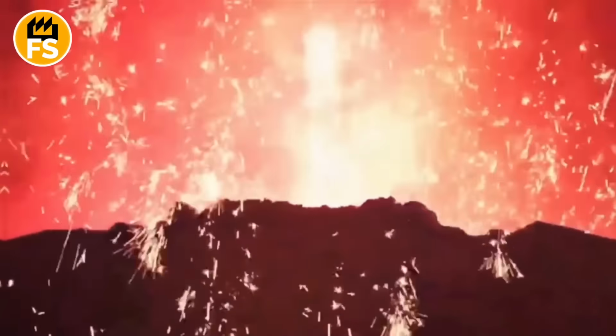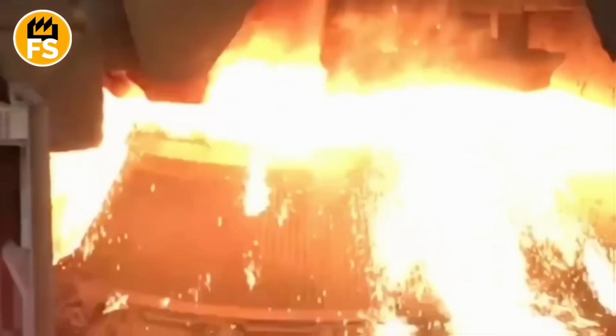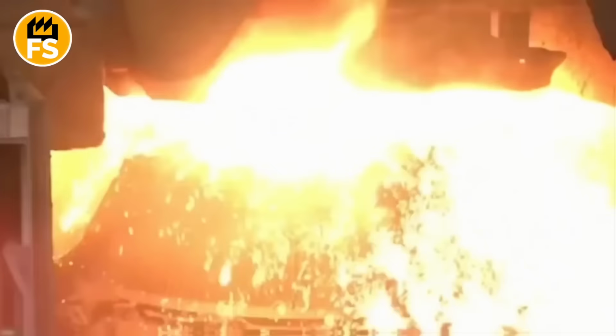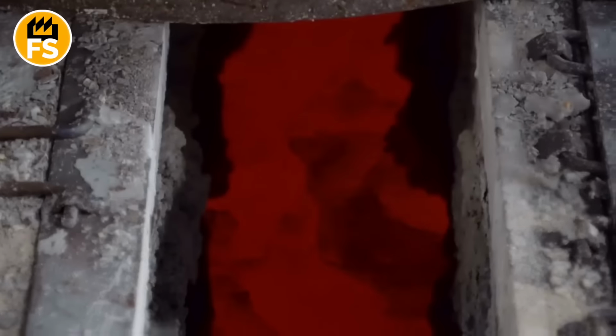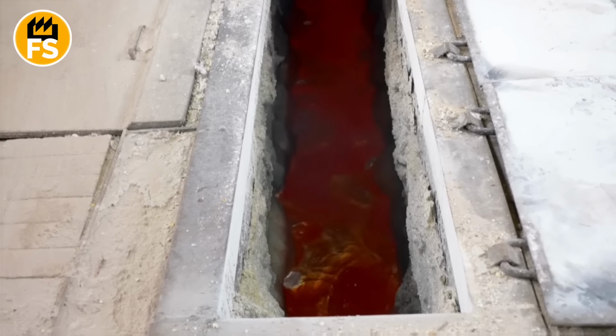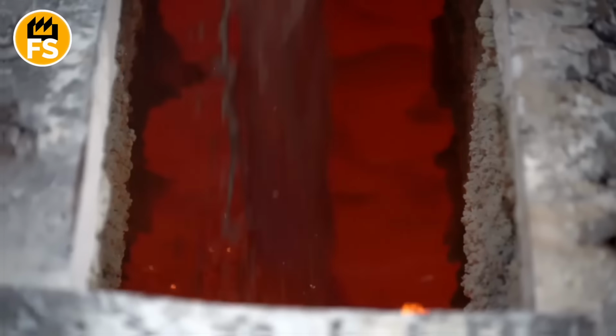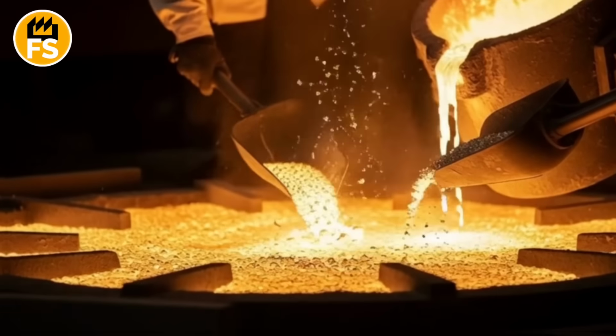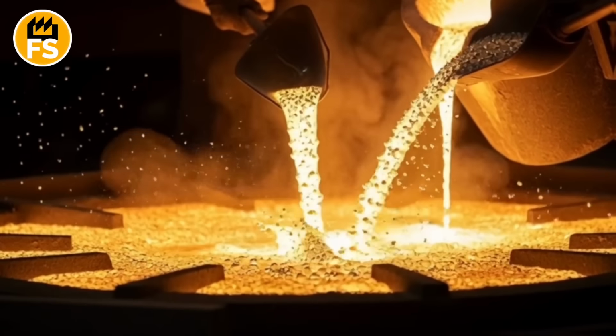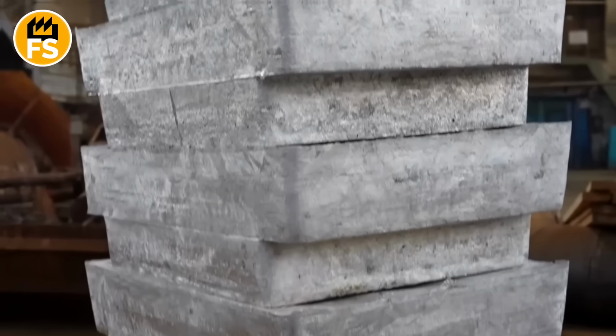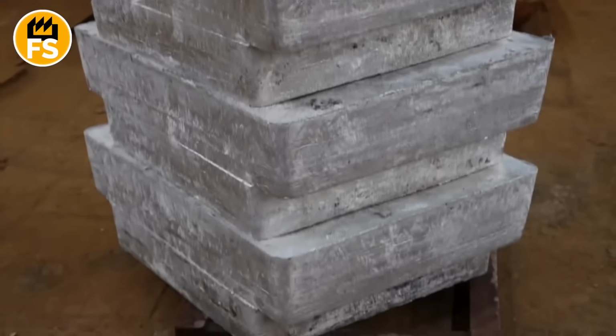The metal chamber walls glow red from the heat, and inside, the molten material looks like incredibly thick, scorching soup. At this point, electric current passes through it. You can only watch through protective windows, because everything inside appears to glow. Magnesium begins separating into tiny droplets that rise to the surface, since their density is lower than the molten mixture. It's collected using special ladles or drainage systems, and eventually the metal accumulates as shiny silver ingots, ready for further purification or casting into molds.